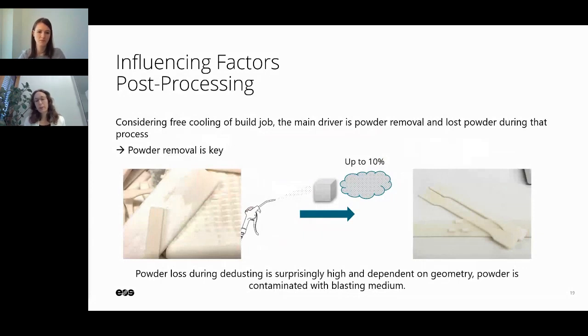The problem is this powder is sticking in cavities and it's sticking to the parts. And even if I try to clean them as much as possible before blasting them, our powder loss is surprisingly high. We have a powder loss of up to 10% of the original used powder because of all these tiny cavities where there's still powder sticking.